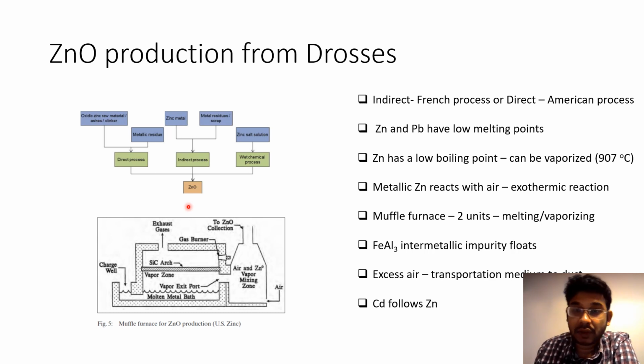And then you have some intricacies. For instance, the excess air also acts as a transportation medium, which helps the collection of zinc oxide, improving the efficiency. Also, this burning, luminescent, exothermic reaction really helps the heat balance of the furnace, because with an exothermic reaction, you don't really need to heat up a lot. So this is the first way to produce zinc oxide from the process.